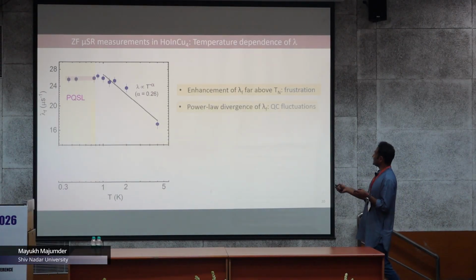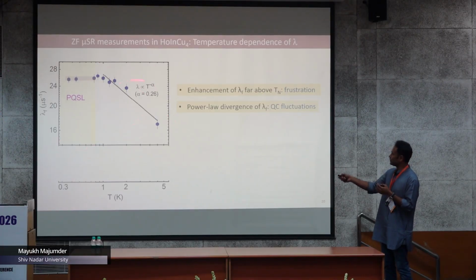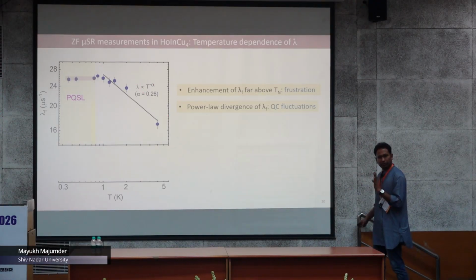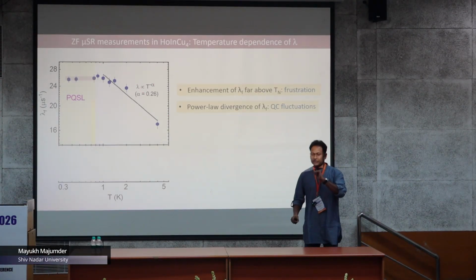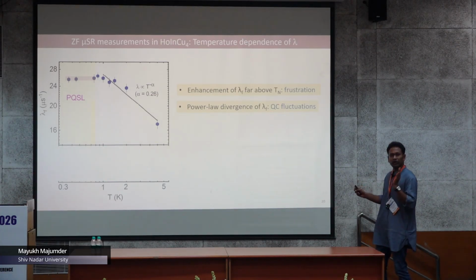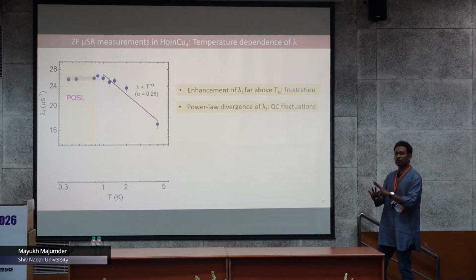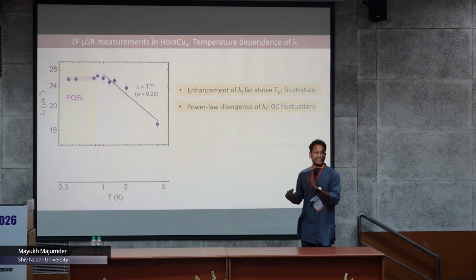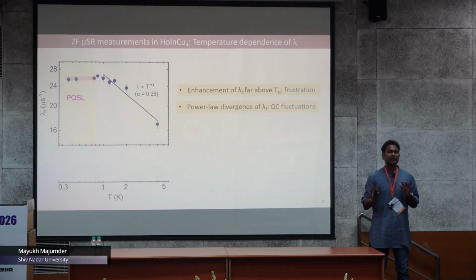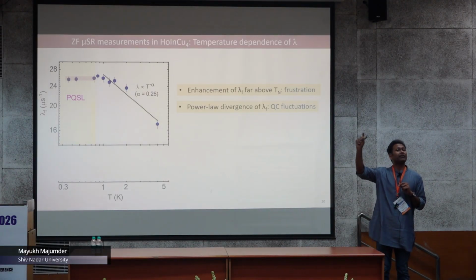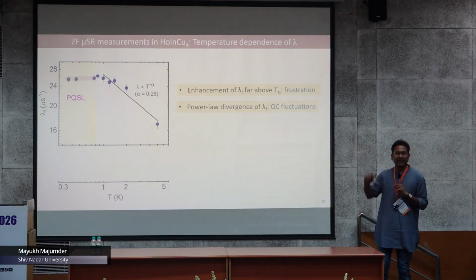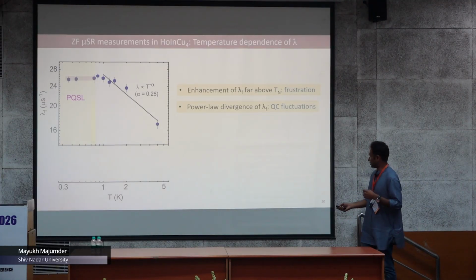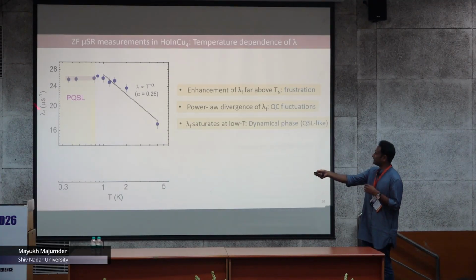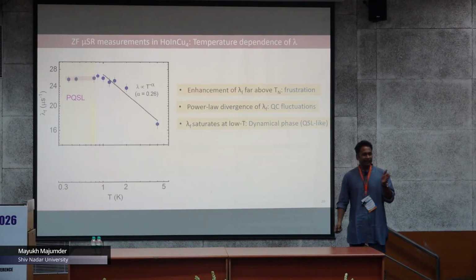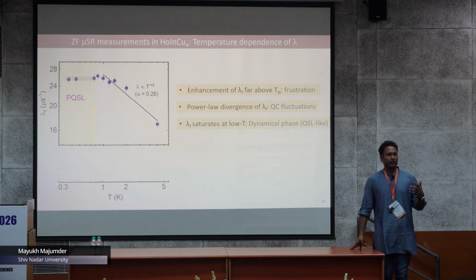Okay, so the next part is that you see a power law divergence with some exponent that might indicate some quantum fluctuation. However, we do not claim that it is definitely a signature of quantum fluctuation. Just keeping that in mind, we realize that the ordering is at very low temperature. There is a good chance that it might show some presence of quantum fluctuation. And the main important point is that lambda f completely saturates below Tn, indicating a similar kind of quantum spin liquid like behavior.